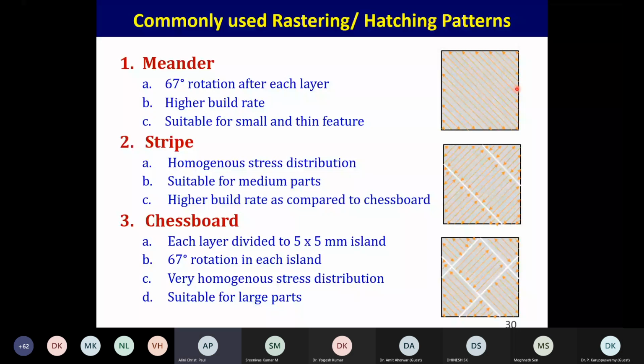Another way is having a stripe deposition. When you have a large surface, just go on depositing like this. Stripes are important because if you have a large surface, for example a plate of say 300 millimeter by 300 millimeter, by the time you go to the end and come back, the heating effect will not be there. So it's better you make small stripes and then go on doing it. That sort of thing people are trying.